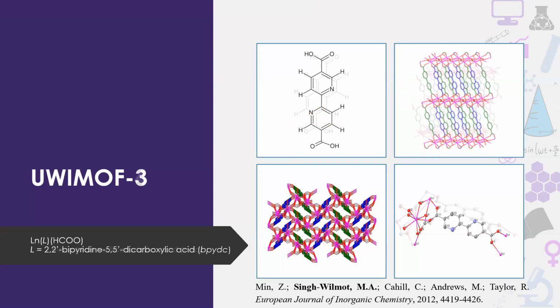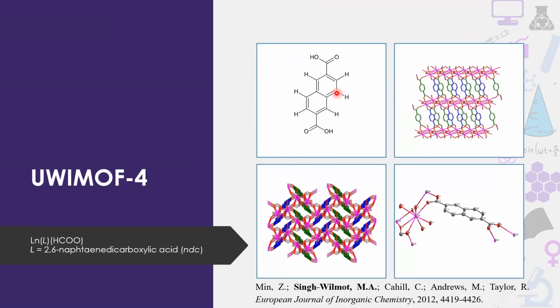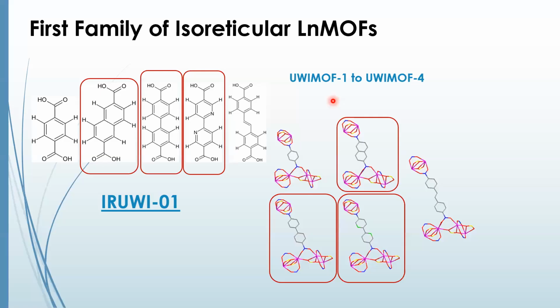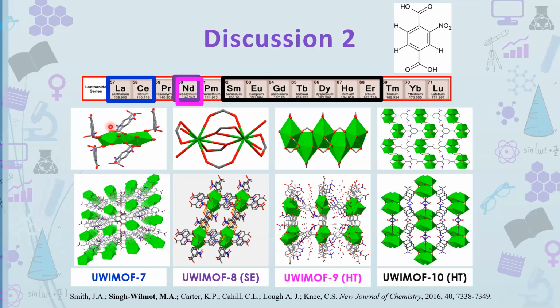Again, we were able to form UWI-MOF 3 and UWI-MOF 4 when we continued to change the functionality. And we reported the first family of isoreticular Ln-MOFs. See, previous to this study, the ability to reticulate was limited because of the variable coordination chemistry of lanthanides; the structures that people would get were unpredictable because lanthanides exist in variable coordination modes. And so it was very difficult to reticulate. So we showed with UWI-MOF 1 to UWI-MOF 4 that we were able to systematically vary the structure of the linker, extending the pore size by extending the linker, and changing the electronic properties of the MOF by changing the electronic properties of the linkers. And we reported that, and it was well received.